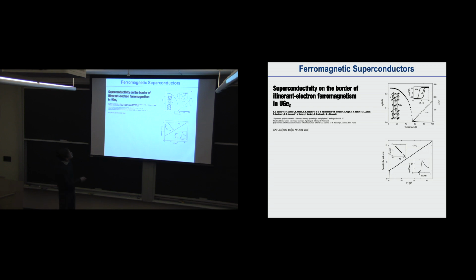The first clear demonstration is uranium-germanium-2, where you clearly see that magnetization appears below something like 50 Kelvin, and superconductivity appears at a few Kelvin-ish temperatures. Therefore you can see there is a coexistence of magnetism, ferromagnetism, and superconductivity.